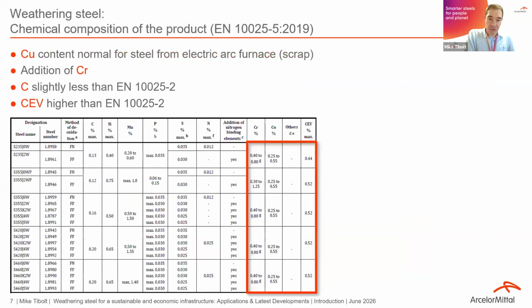If we have a look at the chemical composition of weathering steel, we see that the copper content comes from the electric arc furnace, so when it's produced out from scrap. What is added is chrome, which we need so that the patina forms and also adheres to the base metal. The carbon is slightly less than for non-alloyed steels. However, because we add additional chrome, copper, nickel, and additional alloys, the CEV value is higher than compared to non-alloyed steel. This is what we can see in the table, an excerpt from 10025 part 5.